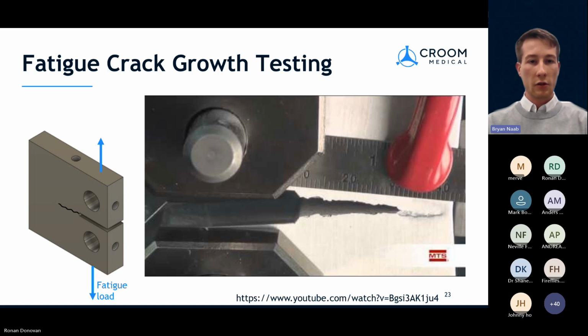And it generates a crack growth curve. And using that crack growth curve, we can infer the maximum critical defect size within a part before fatigue failure will occur, essentially. So this, again, feeds into our inspection, quality control, validation metrics, which we spoke about previously for CT scanning. So we could CT scan an implant essentially and verify that there's no defects of a critical size within that implant, and we can do this based on the fatigue crack growth test.